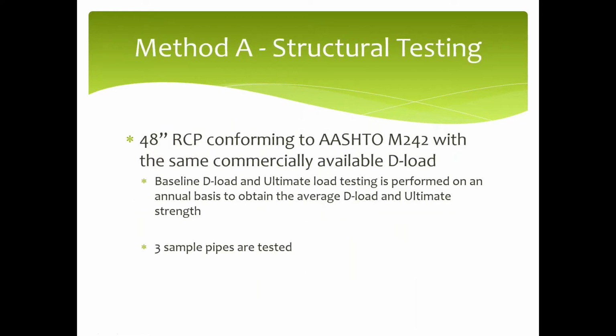So the method A, again, you're looking at a 48-inch reinforced concrete pipe. The first thing we're going to do on an annual basis, according to the work plan, is get a baseline D-load for that pipe, and then a baseline ultimate load for that pipe. So the work plan says you need to go out and get 3 samples of pipe from a vendor that's commercially available D-load. So it could be a 1,000 D-load pipe, 48-inch, whatever's available near the testing lab.